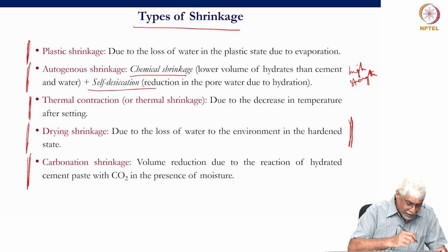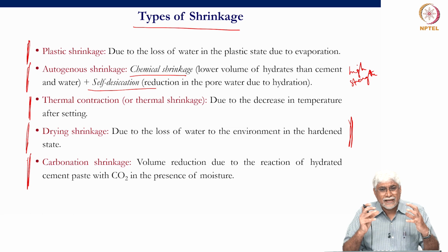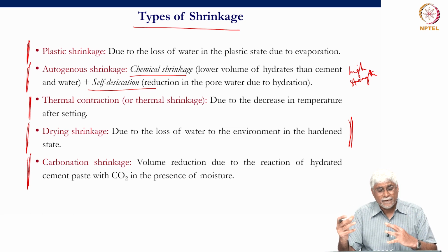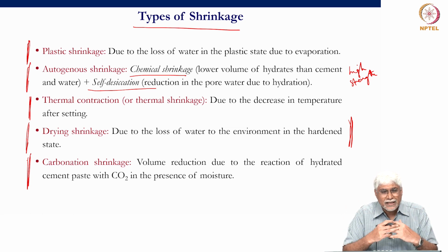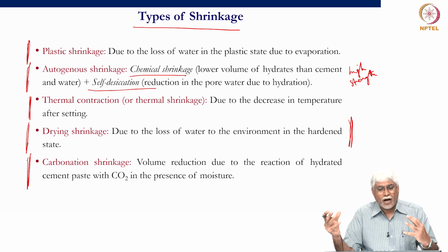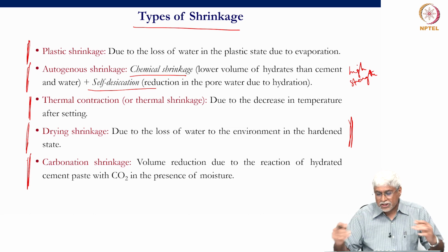The other mechanism, the final mechanism that we'll have to talk about is carbonation shrinkage. So as concrete carbonates, the carbonate products or the products of carbonation decrease volume and release some water. So this gives rise to shrinkage. So if we have carbonatable adhered mortar and this is going to carbonate later and it is going to shrink later, then we will have some effect. But otherwise, mostly what happens is the adhered mortar is carbonated because the aggregates have been stockpiled, have been outside in the environment, and they are carbonated. So we should not have much worry about carbonation shrinkage in concrete with recycled aggregates with respect to concrete with pristine aggregates or natural aggregates.